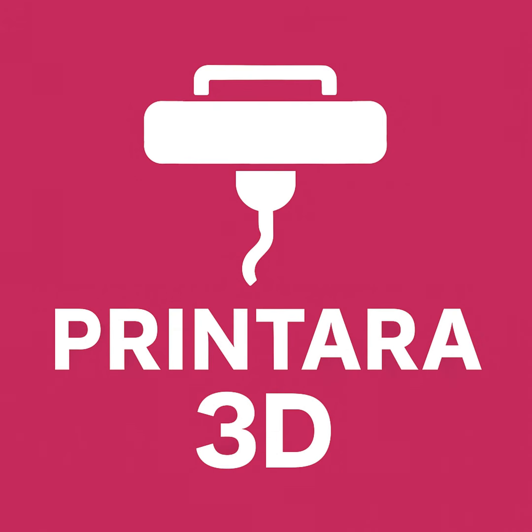What happens if you ignore that? Say you try metal PLA with a cheap brass nozzle. Disaster. The metal particles will just grind away the soft brass. The sources say a brass nozzle can be destroyed, like completely ruined incredibly quickly, sometimes in just a few minutes of printing. Seriously. The nozzle hole widens out, you lose all precision, your extrusion becomes a mess, the nozzle is just toast. Wow. Okay, so step one is buying a hardened steel nozzle. That's an extra cost right away. Yep. Non-negotiable hardware upgrade.